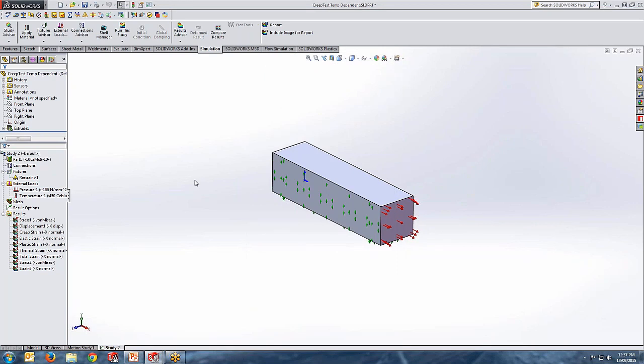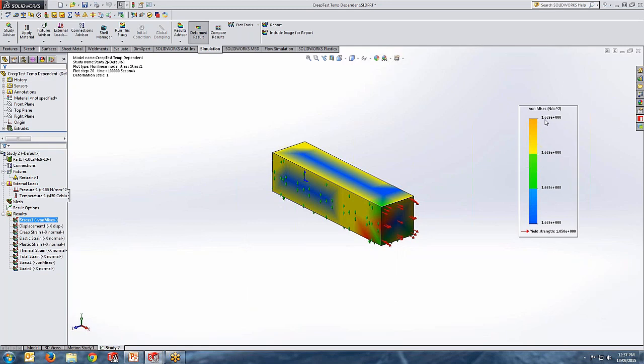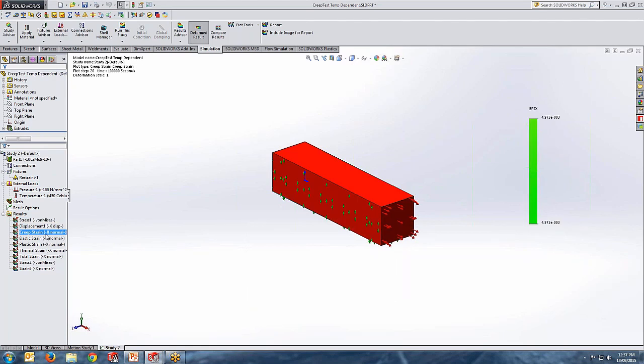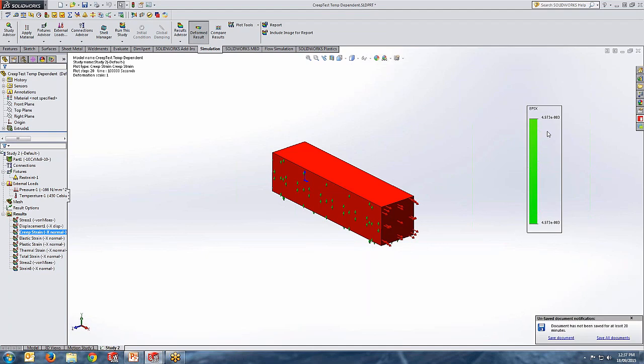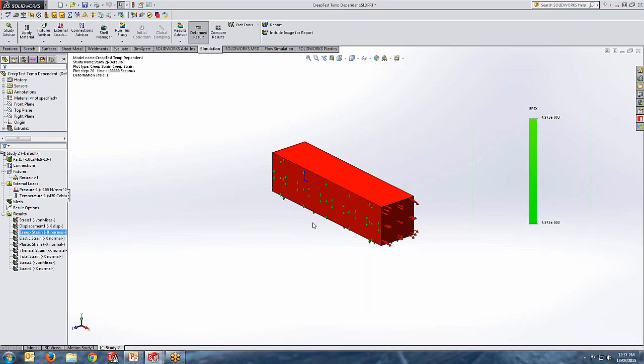After running this application, first we confirm 166 MPa of stress. Looking at the creep strain, we see a very important note: the strain rate is not 1%, it is 0.5% or 0.005. This simply triggers one very important fact — the test data we had from the beginning was not good test data. It has some problem, as this simple example is not producing the same strain rate. Therefore we have to go back and test the data again, making sure the raw data is correct.